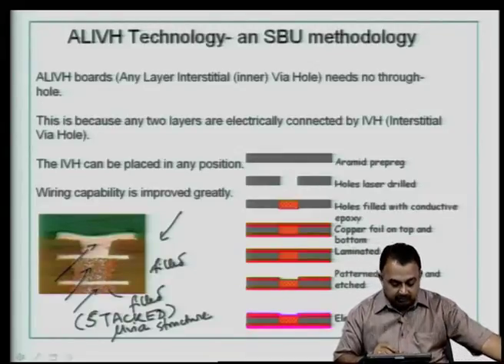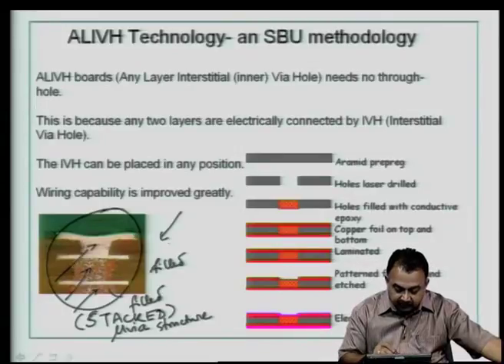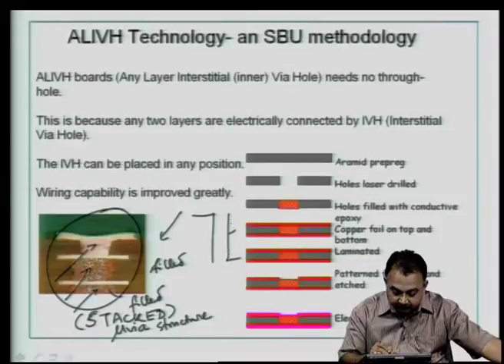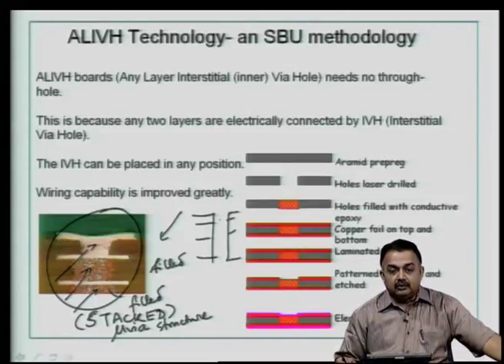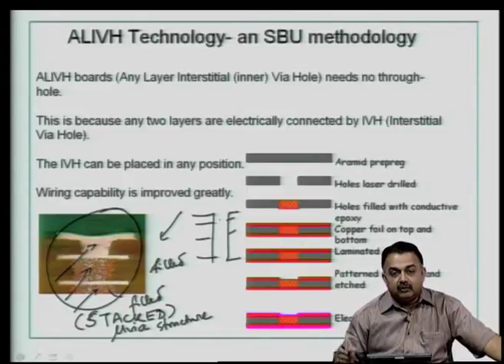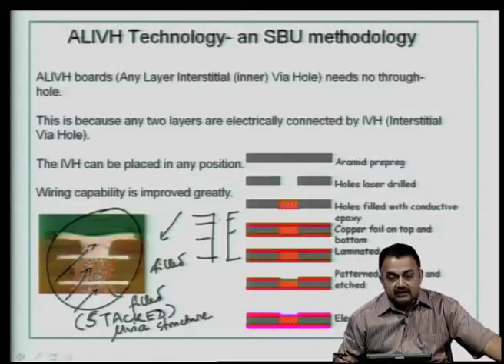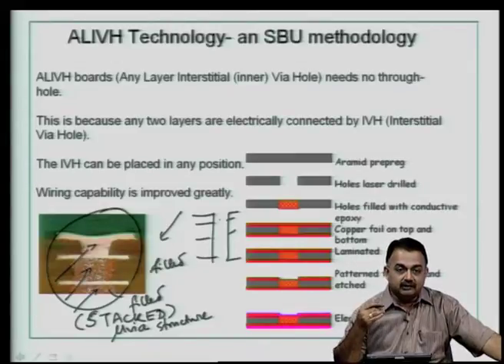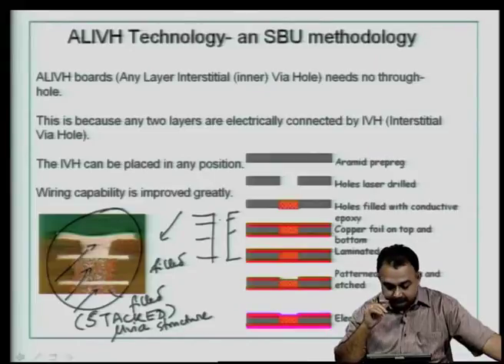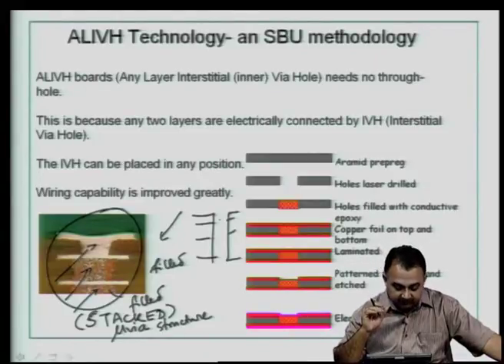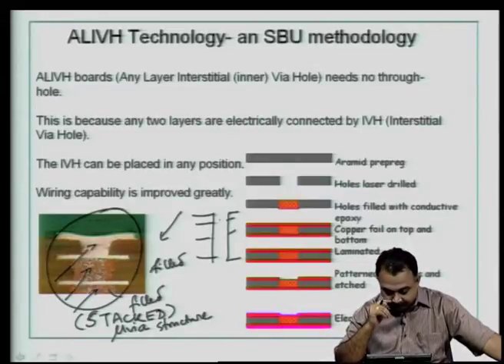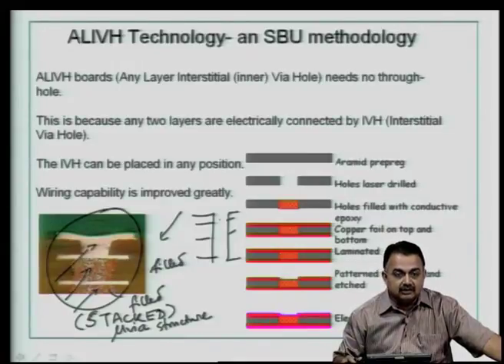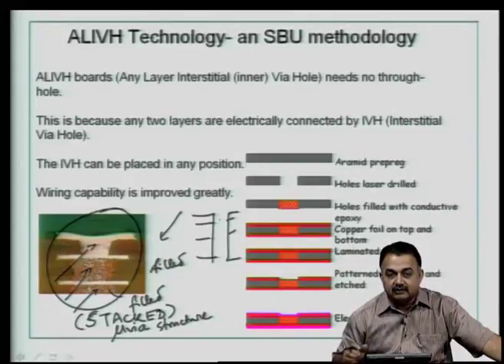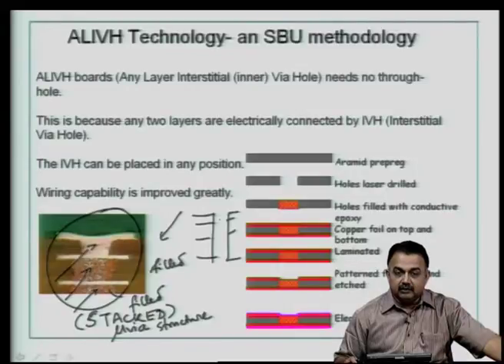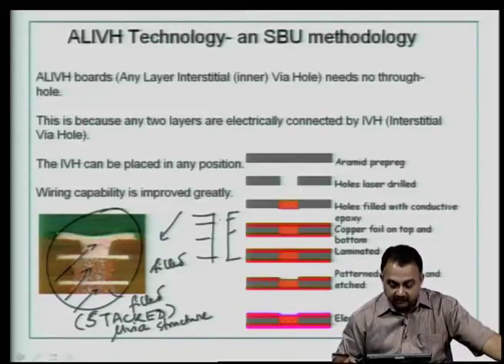Now, there can be questions about the reliability of this stacked microvia structure compared to your through hole structure. So, that is why we say in the case of stacking of a microvia, you do not want to exceed 2 or 3 or 4 layers, because it depends on the conductive paste that you are using to fill the microvia hole structure. The rigidity of the structure is dependent on the properties of the material that you are using to fill the microvia structure, because it should not cave in during your thermal cycling process, and then there should not be too many solvents in the makeup of the conductive paste. There should be no air bubbles or voids, and it should provide very good curing, so that you have very good contact with the adjacent copper structure.